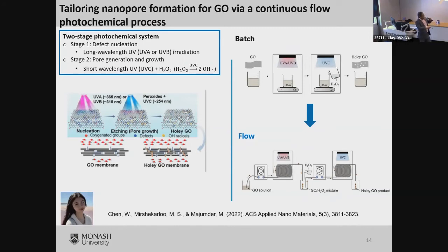So initially, Wanqing started to play in batch chemistry. She developed the method. She developed the conditions under which this occurs, and then she moved on to a flow chemistry approach where you nucleate and then create the defects. Okay, two-stage process. And I think by now, Wanqing has a method which is fully continuous. Moving from batch to fully continuous mode, she is now able to produce these materials in the lab.